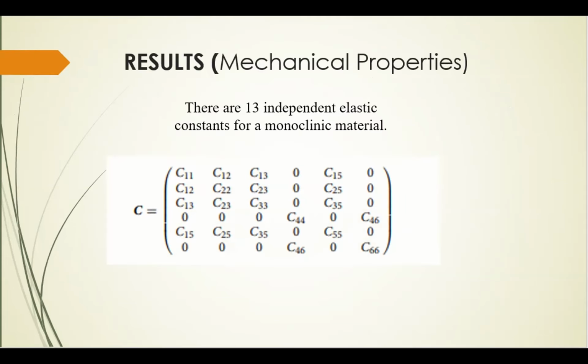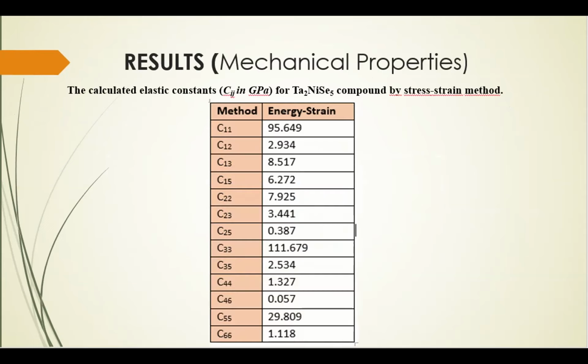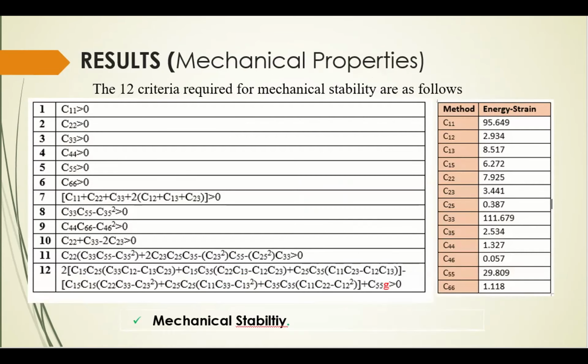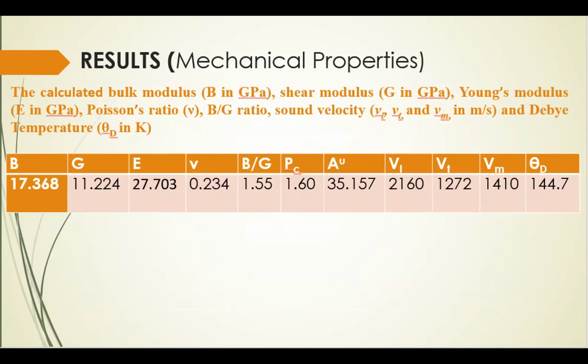There are 13 independent elastic constants for a monoclinic material. The second-order elastic constants of the compound were calculated by means of the stress-strain method based on first principles calculations. Polycrystalline elastic moduli are calculated using the Voigt-Reuss-Hill approximation. It has been determined that the compound satisfies the stability conditions for a monoclinic structure and it is mechanically stable. Polycrystalline elastic moduli were calculated with the help of the obtained elastic constants.